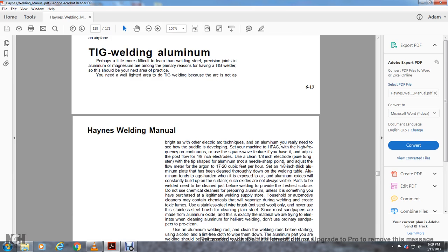Adjusting the flow meter for the argon to 17 to 20 cubic feet per hour, with a set of 1/8 of an inch thick aluminum plate thoroughly clamped down on the welding table. Aluminum tends to harden with age. When exposed to air, aluminum oxide will constantly build up on the surface. Such oxides are not always visible. Parts to be welded need to be cleaned just before welding to provide a free surface.